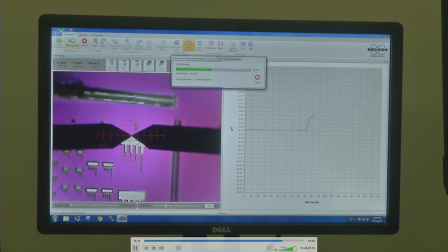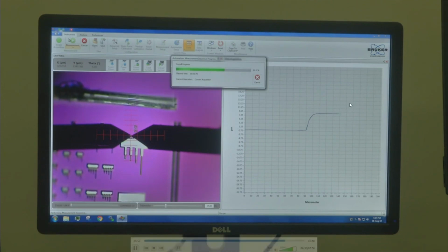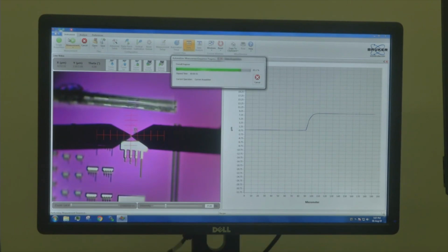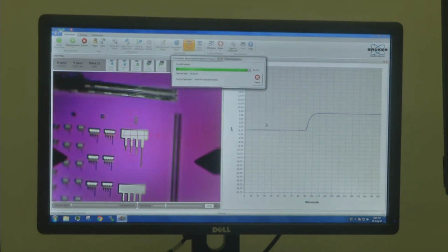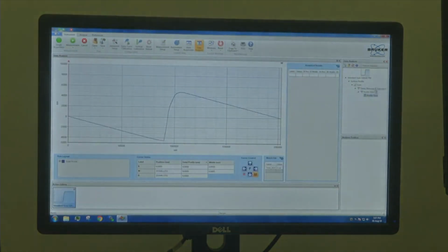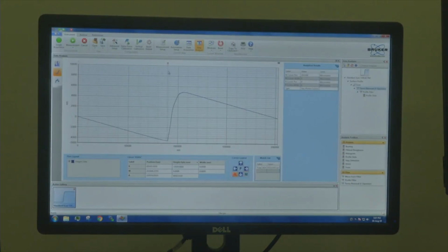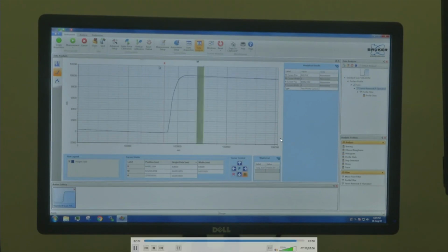See? So there is a change in the thickness, as you can see here, a sudden change in the thickness that we see. And this thickness change is because we have etched this film, right? So we have to do some baseline correction. So it is tilted. So once you do the baseline correction, we'll see the height difference that we get. So from the left side to the right side,